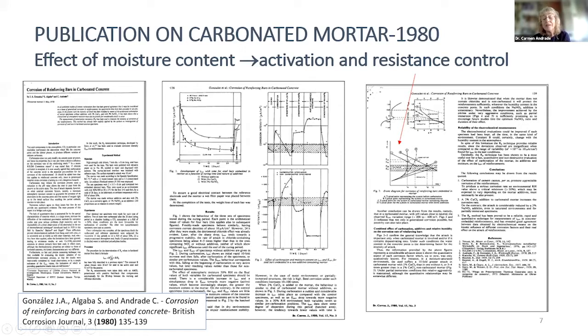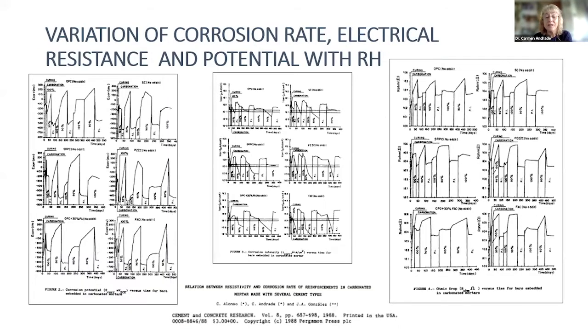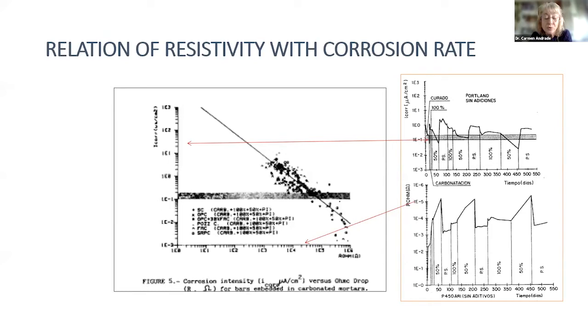And we stated that the mechanism or the control of the corrosion in concrete can be an activation control, but also mainly a resistance control. And this is very old, back in the experiments. We did that in many cases with chlorides, with inhibitors, and we were able, together with Gonzalez, to plot this graph that I show here, in which we present the corrosion rate versus the resistance of the mortar, the ohmic resistance. And we realized this resistance control that we were commenting.